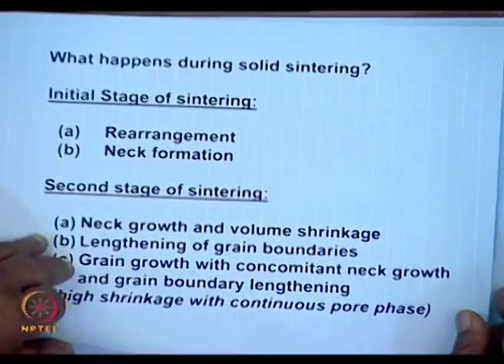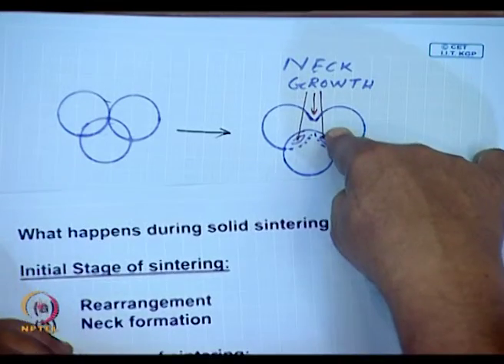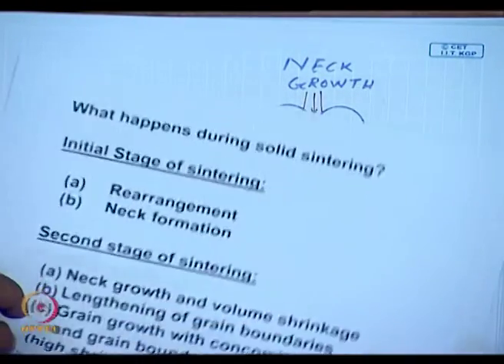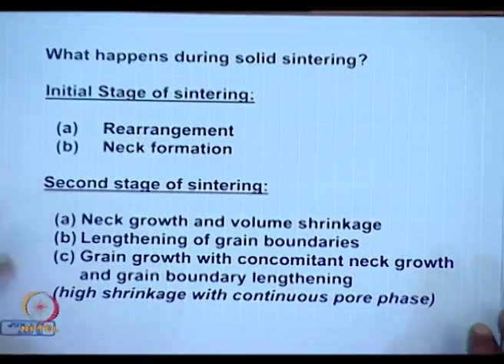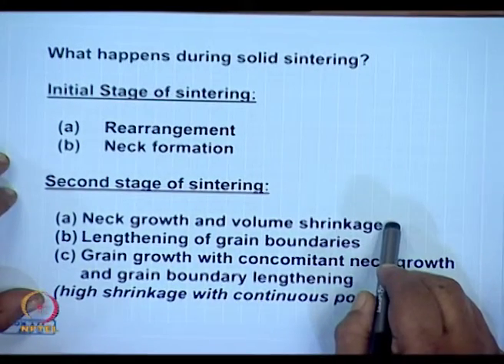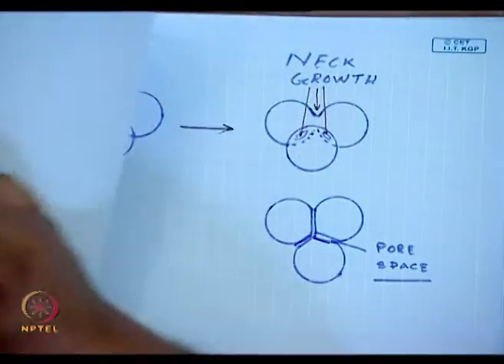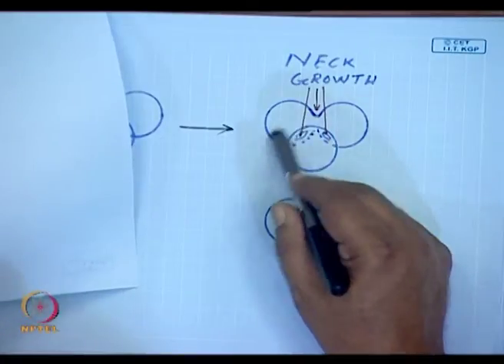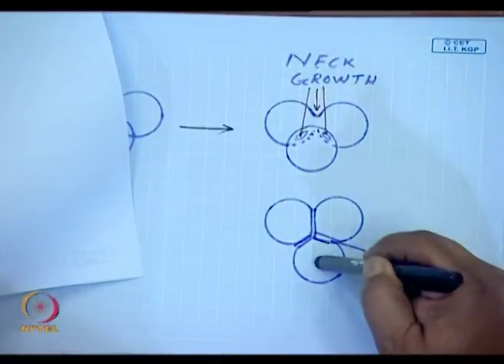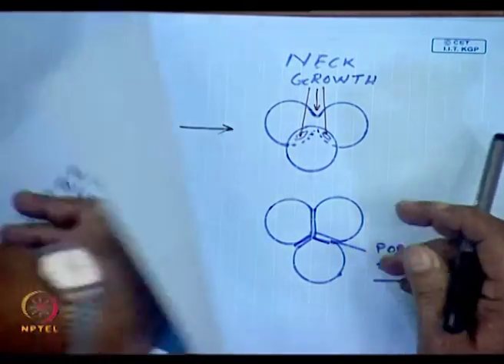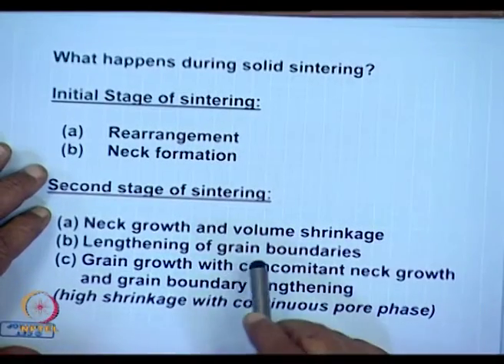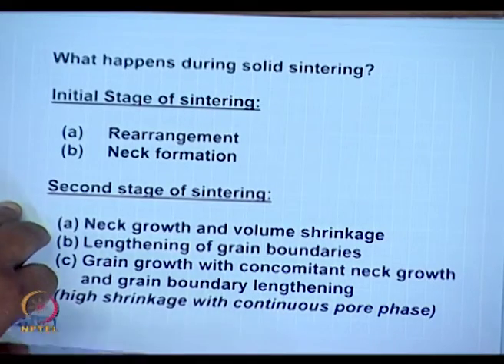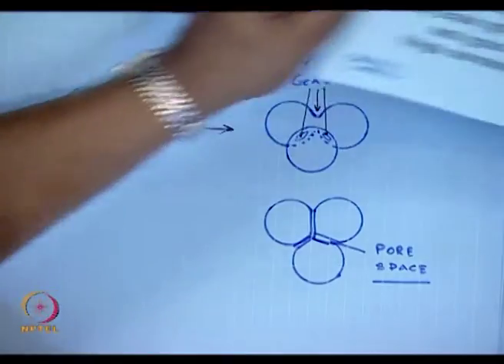At the second stage, which is the intermediate stage, what we have is neck growth and volume shrinkage. If these necks grow larger and larger, it means the packing is increasing, which you can see over here. Lengthening of grain boundaries - let me say what it means.